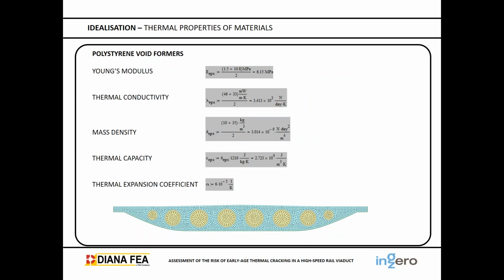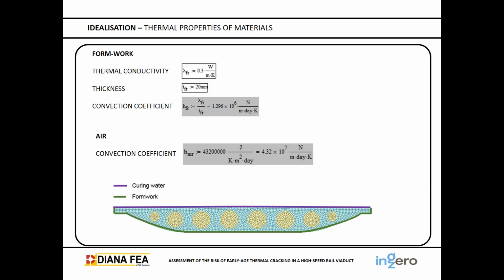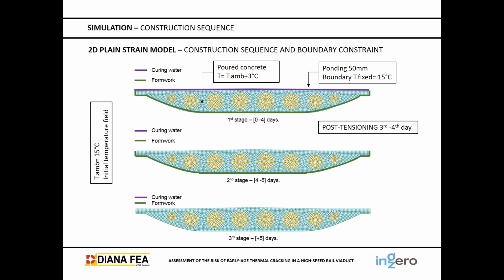Also for the other materials which we simulate, which was the polystyrene void formers, we have Young's modulus, thermal conductivity, mass density, thermal capacity, and thermal expansion coefficient. Also for the formwork we represent in the model, we have the thermal conductivity, the thickness, and the convection coefficient, and from the air, the convection coefficient. Those two, formwork and air, we represent like a boundary condition, okay, in which you can transfer heat. Here is again the construction sequence, but after having seen all the parameters we have entered, we can understand a little bit more. We have an initial temperature field, which is the ambient temperature of 15 degrees.